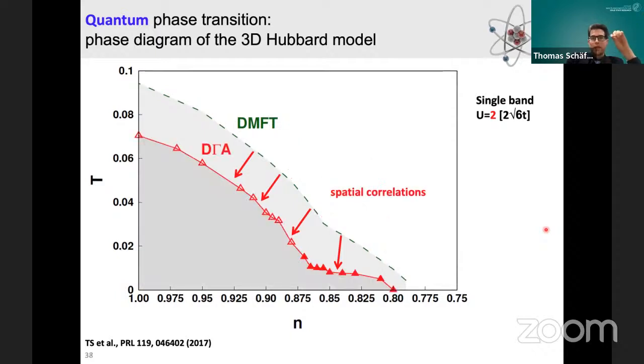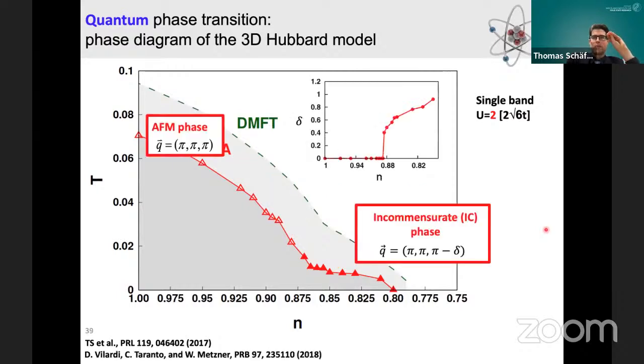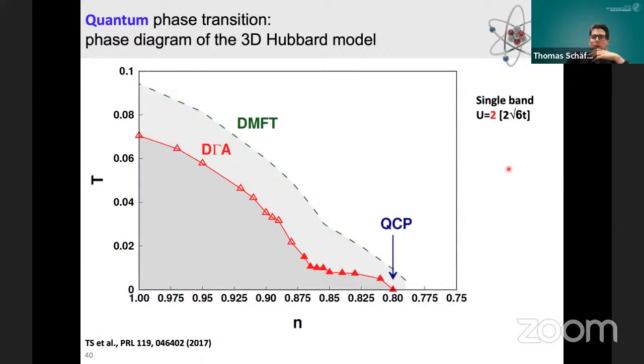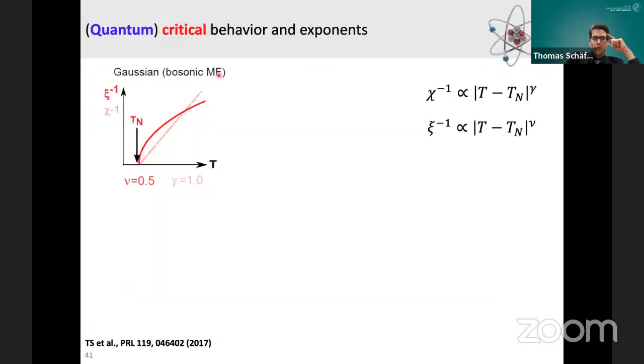And what is also interesting is that we don't get a pure antiferromagnetic phase transition anymore throughout the whole phase diagram. But at low doping, we get indeed still this antiferromagnetic phase, but at larger doping, we get the so-called incommensurate phase, which you can view as a spin spiral, so to say, spiraling from one lattice site to another. What we also get is a quench of the transition to T equals 0. So we want to analyze now the quantum critical point there. There we can think of what we expect for the quantum critical exponents at this quantum critical point. Well, before I showed you that the DMFT as a mean field theory shows this critical exponent of 1 for the susceptibility. It would show for the correlation length a critical exponent of ν equals 0.5.